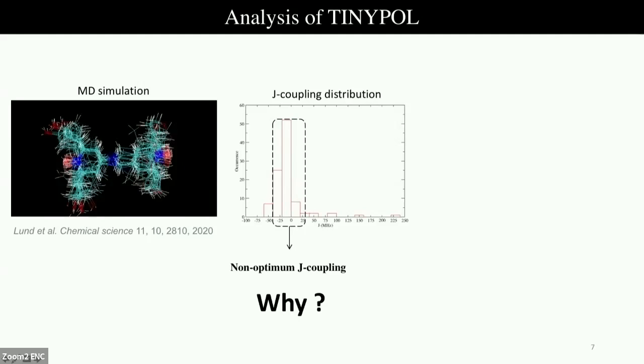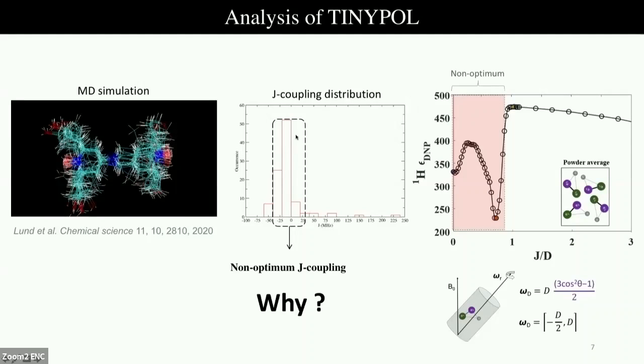TinyPol is a very flexible molecule, so it has a distribution of J coupling. The most probable J coupling in TinyPol is accidentally not optimum. By optimum, I mean the ratio of J coupling and dipolar coupling is less than 1 in TinyPol. Such orientations, where the ratio of J and dipolar is less than 1, lead to inefficient DNP because of interference between dipolar and J coupling. Dipolar coupling, you all know, is anisotropic, so it can have both positive and negative values, but J coupling is scalar. So it may happen that for certain orientations, we are having effectively very small coupling, and all those orientations lead to very poor DNP.